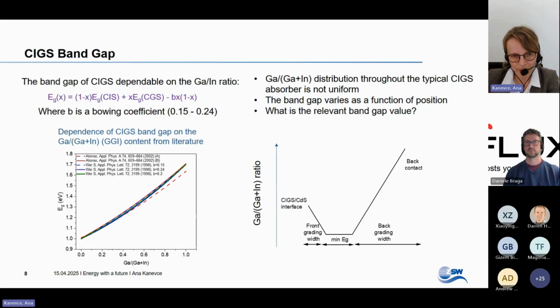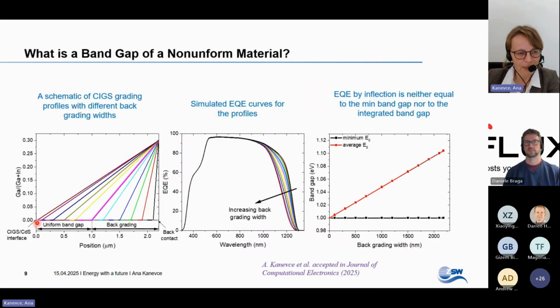Now to try to answer this, I simulated in SCAPS grading profiles like this. So the GGI and the bandgap were uniform for a while, and then started linearly increasing after a while. And here are the simulated QE curves of all of these profiles. Of course, the wider the grading extends, the softer the slope of the QE curve is. Now, what will this QE give me?